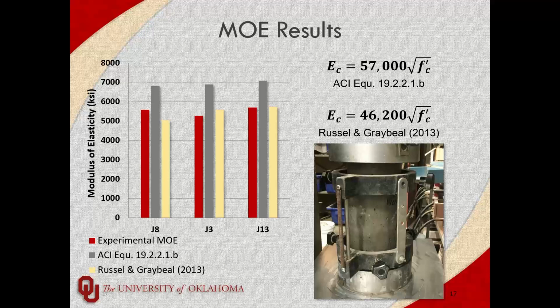The last characterization we did was the modulus of elasticity, and we compared it to 2 different equations. One, the typical ACI equation for normal weight concrete, and then Russel and Graybeal, some of the earlier pioneers of UHPC, they developed a relationship similar to the one for normal strength concrete for UHPC, and you'll notice it's a smaller multiplier, which